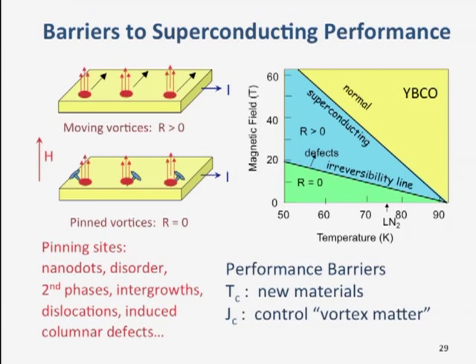So the barrier to superconducting performance is pinning the centers. This is what I was saying before, you have to pin the vortices. How do you do that? We're looking at that in our center, besides understanding the physical properties, is different ways of pinning those. One of the ways we do it is using ion channels. You run a channel through with ions, and recently, in the past few months, we've done protons, and those make line defects, and you collect the vortices like a string of pearls, and so that pins them.